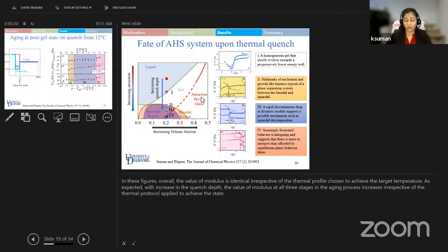Yeah, it can be one of the challenges, but also in the literature, Zaccarelli and others have done simulations for adhesive hard spheres, and they found the rigidity percolation line where the number of contacts of each particle is found to be 2.4. It can be seen that this system follows that rigidity percolation line, which suggests that it is quite close to adhesive hard spheres. So I think maybe we can draw some analogy and try to simulate things as a starting step, to get things easier and then go into more complicated things.